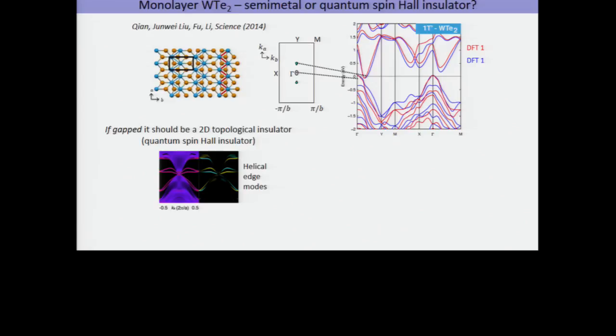Massive semi-metals. There's been remarkably little work on this, I think, and there's a good reason for it too, which is that almost all of these materials are not very stable. Their surfaces oxidize. You want to play games down in this limit, you have to deal with their chemical instability. And so all the progress being made recently on this material and others is by working with them in a very carefully controlled environment, right? Preparing these monolayer devices in a glove box. And that's what is basically allowing us to do these experiments. It's the key thing.